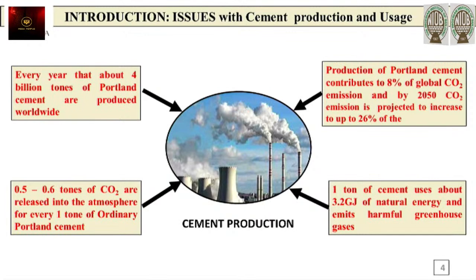And the issue with cement production and usage is mainly the quantity of cement that is produced annually worldwide. If you can see this slide, about 4 billion tons of Portland cement are produced worldwide yearly. As a result, it has led to global warming, and in the production process of Portland cement, a lot of energy is consumed. About 1 ton of cement will consume about 3.2 gigajoules of energy, and this emits harmful greenhouse gases, which eventually lead to global warming, which we are experiencing now.